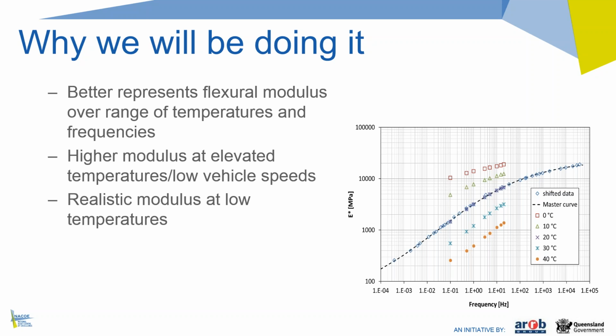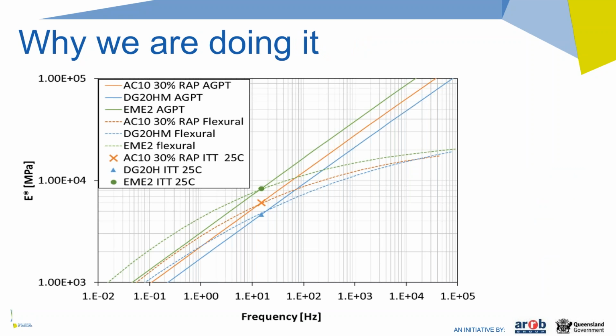So this is an important slide. It basically compares the relationship between frequency and modulus as predicted by Austroads versus what an actual measured flexural master curve would give you. So the markers that you see in about the middle of the slide represent the resilient modulus results that you would get for different mixes.